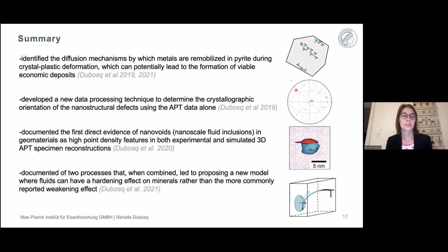And I was also able to document the first direct evidence of nanovoids, or in this case, nanoscale fluid inclusions in geomaterials, as high point density features in both experimental and simulated 3D APT specimen reconstructions. And this finding, or this achievement, led me to document two processes that, when combined, led to proposing a new model where fluids can have a hardening effect on minerals rather than the more commonly reported weakening effect.